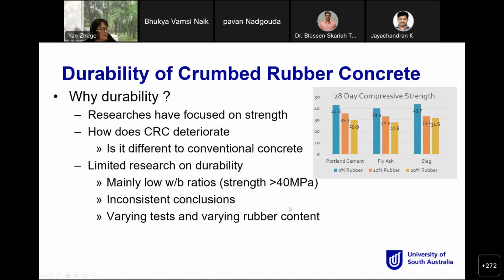And the research, as I said, was quite limited. Major research was limited to low water binder ratio, so that means they produce very high strength concrete. Because our research is more focused on residential construction, and we know for residential construction the compressive requirement is very low, about 25 megapascals. So that's why the durability tests we're doing were more focused on low strength concrete, not high strength. And also the results people got were quite inconsistent for each different durability performance. So that's why more research was required.